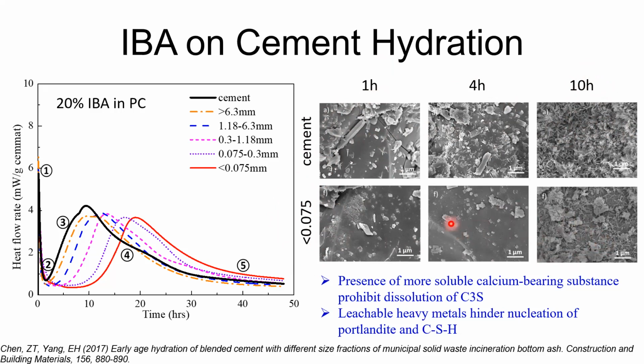This is pretty much because of the presence of more soluble calcium-bearing substance, as we mentioned, mainly in the smaller particles. This prohibits the dissolution of the tricalcium silicate, and therefore delays the hydration.